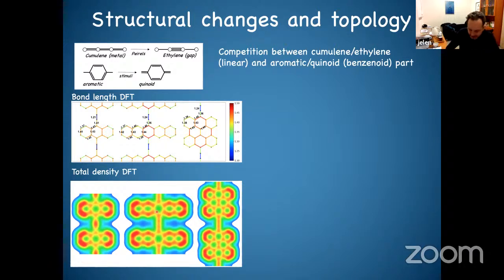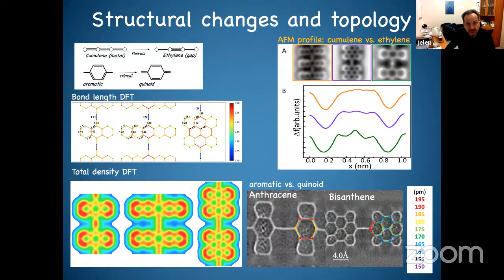And going back again, in this high resolution imaging, when we are very close, this bending of the CO is caused by Pauli repulsion. So basically you try to penetrate one orbital into the other, so the CO starts to bend because there is strong Pauli repulsion. And this Pauli repulsion is proportional to the local electron density. So it means that in this particular case, there should be a much stronger signal in AFM than in this case. And indeed, when we start to look at details of this bond, what you will find is there is a much brighter spot in AFM, which means that there is more electron density here, okay? And this is not found in these two topologically non-trivial states. So you see, this is this line here, and this is the AFM signal.